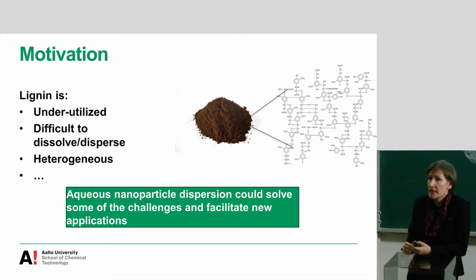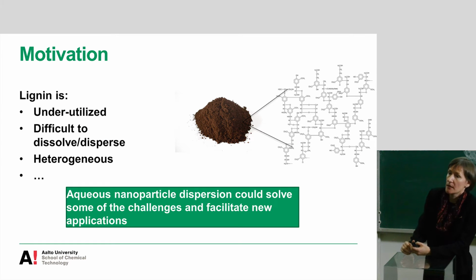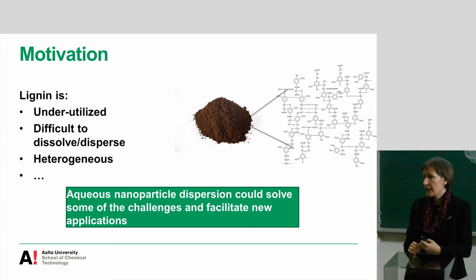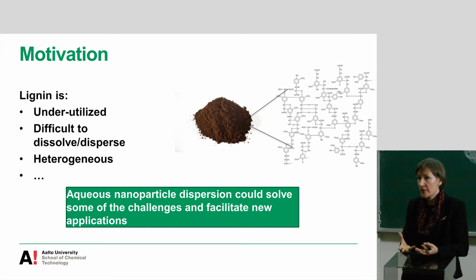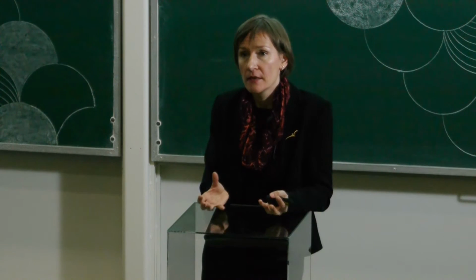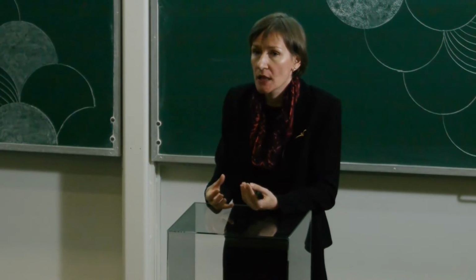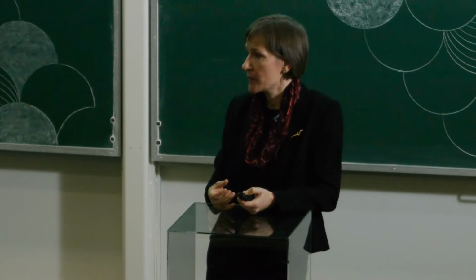So the motivation for this research was that lignin is underutilized, and that's because it's smelly and has a color, but it's also because it's difficult to dissolve and disperse, and it's quite heterogeneous. Our idea was that if we can make an aqueous dispersion of more well-defined spherical nanoparticles or colloidal particles, and we can modify the surface of this, then it would be much easier to utilize, and we could overcome some of these problems.